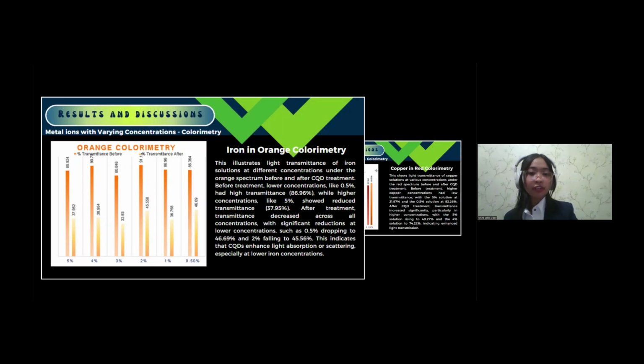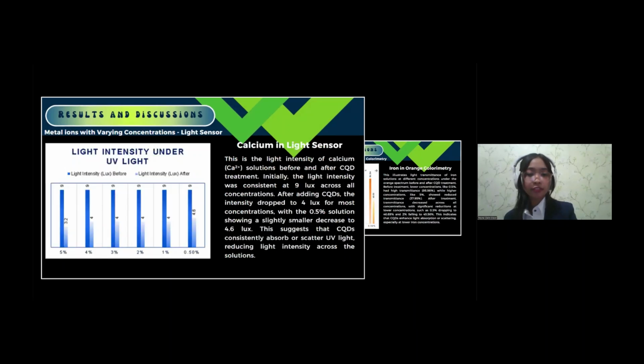Next, we have a figure that shows the before and after adding CQDs. Calcium solutions all had the same light intensity of 9 lux. After adding CQDs, the light intensity dropped to about 4 lux for most concentrations, except at the lowest, where it only dropped a bit to 4.6 lux. This means that the CQDs are absorbing or scattering the UV light pretty evenly across different calcium levels.